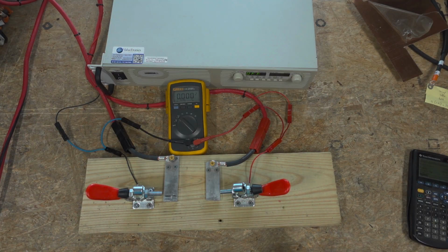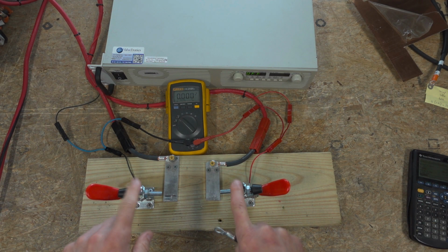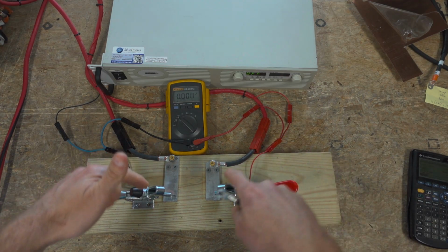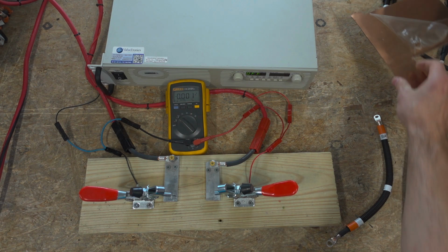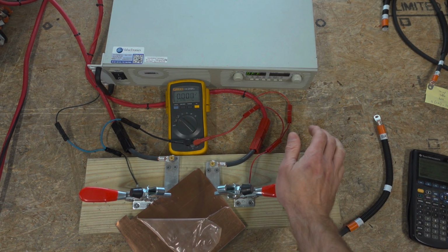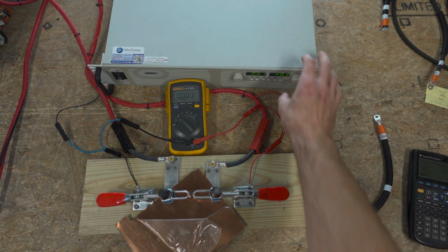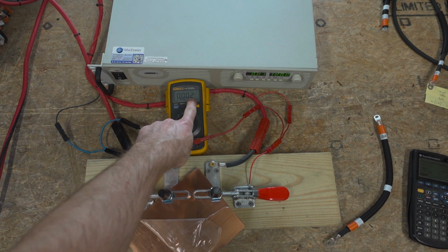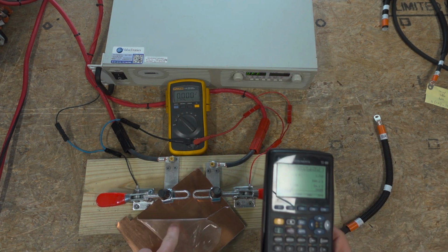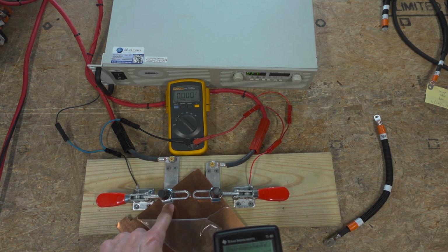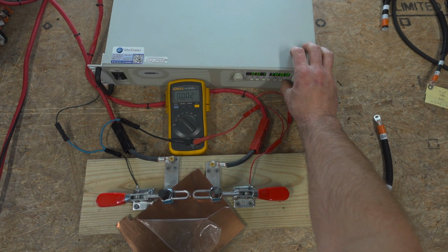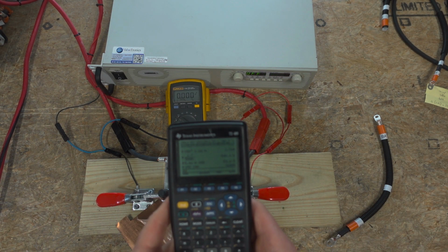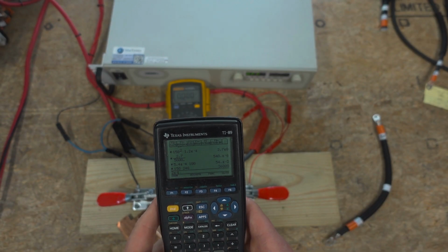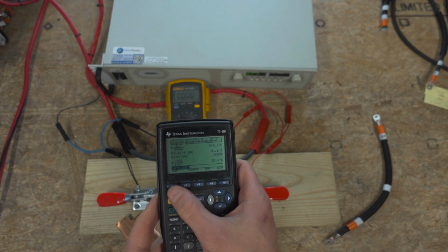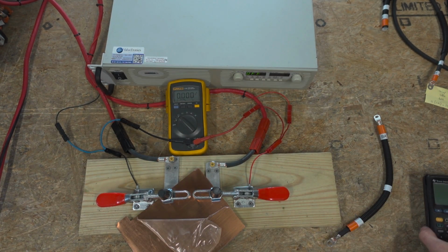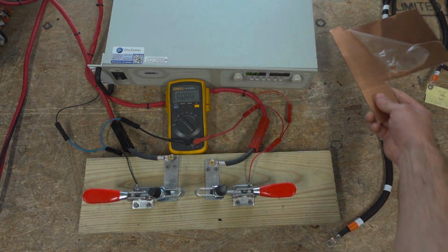I have these two toggles, and our current runs through these bars here, and then we measure the voltage on these tops here. There's basically no current running through this. And the way we can validate that this test fixture works right is you can take a big piece of copper and put it on the test fixture like that, and then put 100 amps through it. You can see we measure a 2 millivolt drop at 100 amps. We're only measuring the voltage drop in the copper in that case. So what was the value again? Sorry, 2 millivolts. So we're talking about 2 millivolts divided by 100 amps, 20 micro ohms through this copper plate here. So that's just the test setup showing that it works.